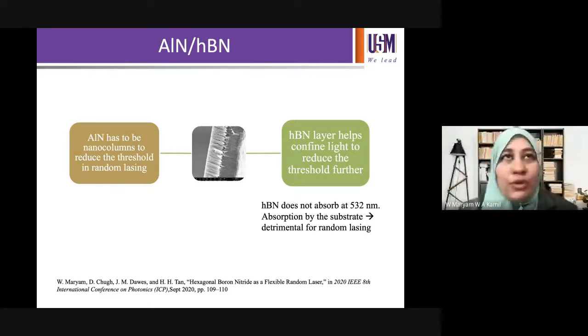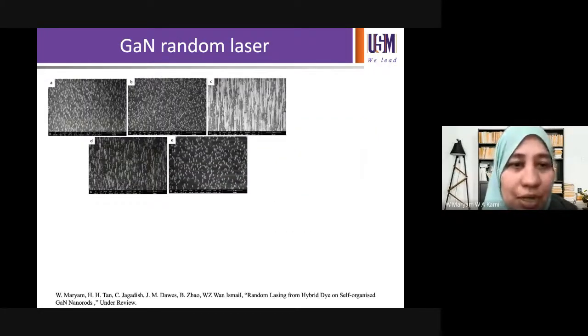Okay, so this is partly the issue with random lasers, and it's partly why you don't see random lasing occurring in all samples. Okay, it may be that in some samples the substrate is absorbing much more, therefore the absorption is playing a much bigger role rather than the scattering effects. And we also notice that it has to be nanorods. Okay, when we looked into gallium nitride, this was also prepared by metal organic chemical vapor deposition, MOCVD, in ANU.